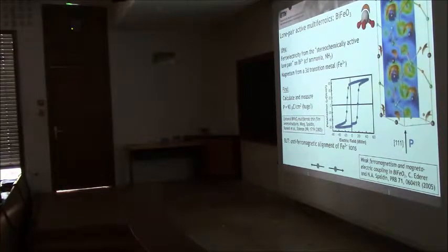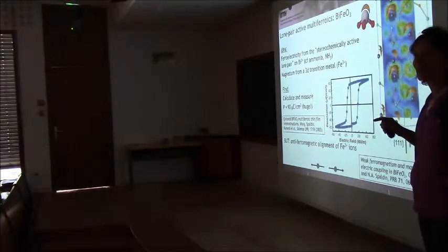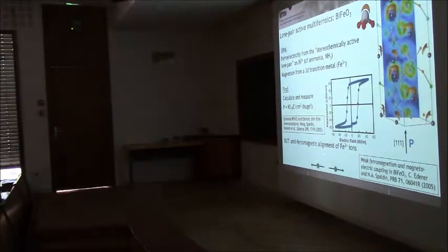Of course, the problem with bismuth iron oxide, and this is the problem with, I'd say, most insulating magnetic transition metal oxides, is that they're anti-ferromagnetic because of the superexchange interaction. And so rather than having a ferromagnetic ferroelectric, one has an anti-ferromagnetic ferroelectric, which is very strong. The anti-ferromagnetic superexchange between d5 ions is extremely strong. So this was not optimal. What saves bismuth ferrite a little bit is that there's a canting of the anti-ferromagnetic moments, which gives a small, weak ferromagnetism, and this has been exploited. This has been exploited actually to allow a magnetoelectric coupling, but it's not as desirable as having a ferromagnetic ferroelectric.